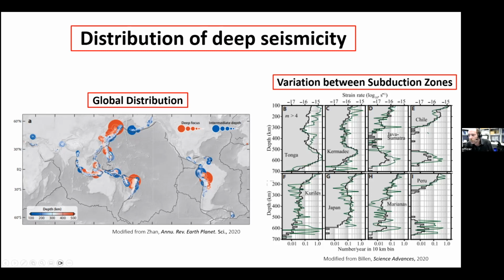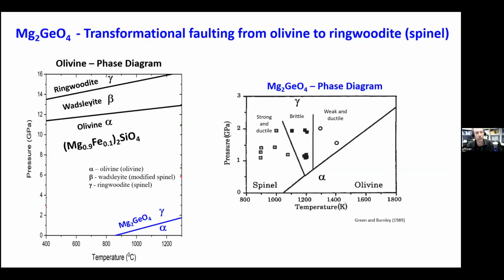On the South America ones, they have a total absence of seismicity between about 300 and 600, but then these jumps. So depending on which subduction zone you look at, the seismicity can vary pretty dramatically. Now, it would be very nice to test this hypothesis, like let's take some olivine and transform it and get it to break. But it's very difficult in a deformation apparatus to reach the pressures, and the temperatures are easy, but to reach the pressures required to transform olivine to wadsleyite or ringwoodite.